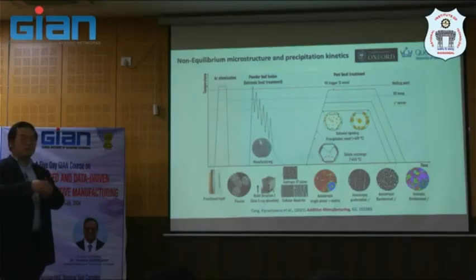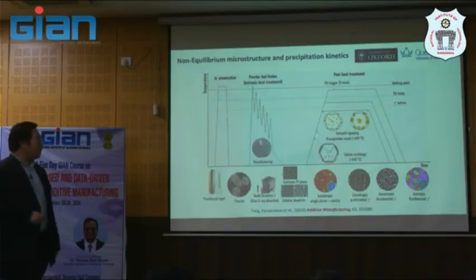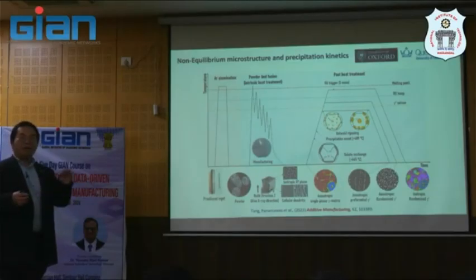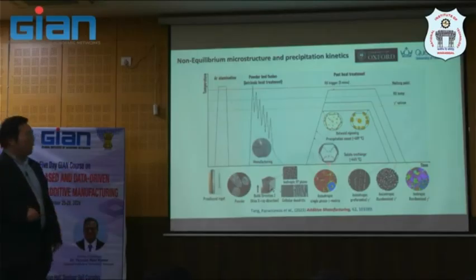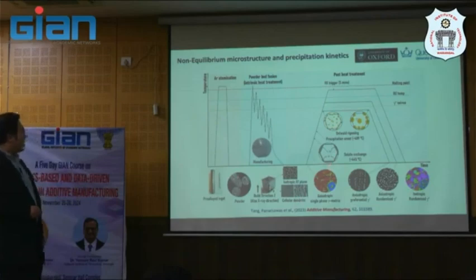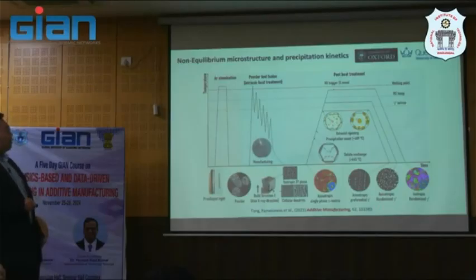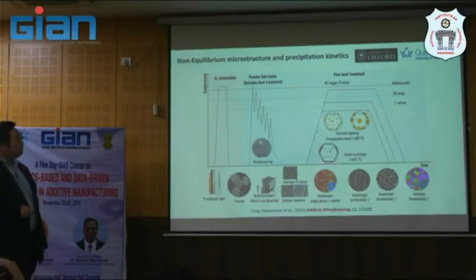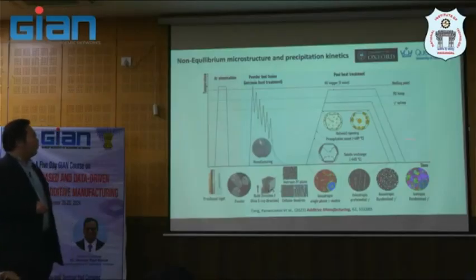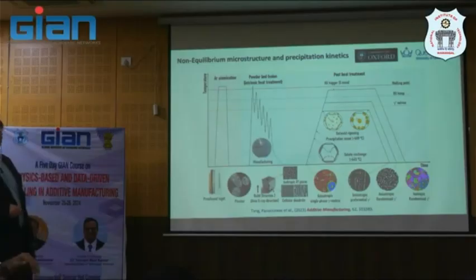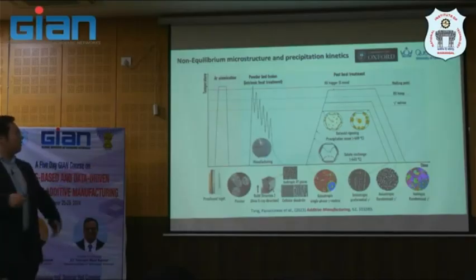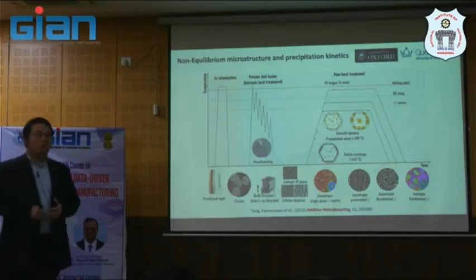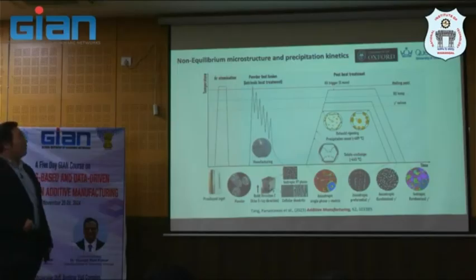When I say anisotropic, it's not in terms of orientation only, but in terms of the phases present during printing. So you get gamma. In nickel-based superalloy, it will be gamma prime, but you may get only gamma with a small amount of gamma prime. We will show you more tomorrow as well. Then there is some anisotropy, which happens with preferential gamma prime, and anisotropy of the randomized gamma prime can happen in the post treatment. And actually, you want to get to an isotropic gamma prime distribution in the end because you want a more homogenized structure for the property and material life.